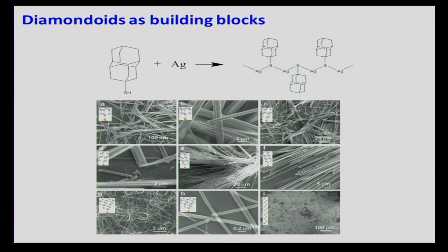People know that when you put these two things together, the silver or the metal species bind with the sulfur, and they form a long chain of alternating metal-sulfur, sort of like a polymer, but instead of a polymer being formed by carbon-carbon bond, this is formed by a metal-sulfur bond. And then you have the diamondoid sitting around them like a side group or like a shell. Now what's unique here is that we tried a lot of different diamondoids as well as other hydrocarbon species with a sulfur atom at its end.